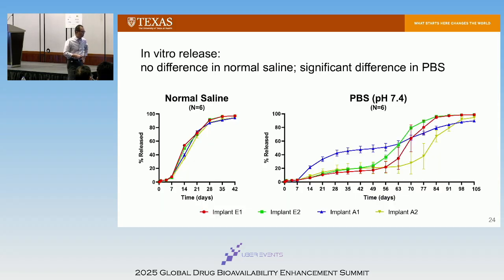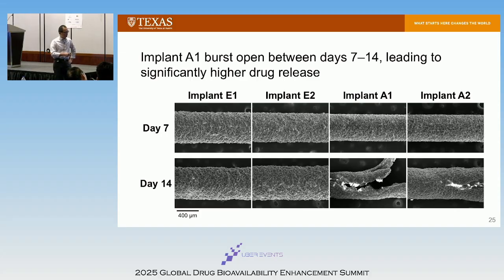That's what's caused. There's an osmotic effect, right? When the polymer degrades, they become oligomers, but they cannot diffuse out, so water wants to come in. So implants will swell to some extent, and they can cause rupture of the implants.